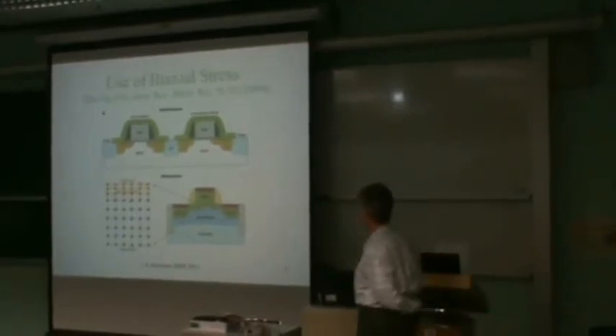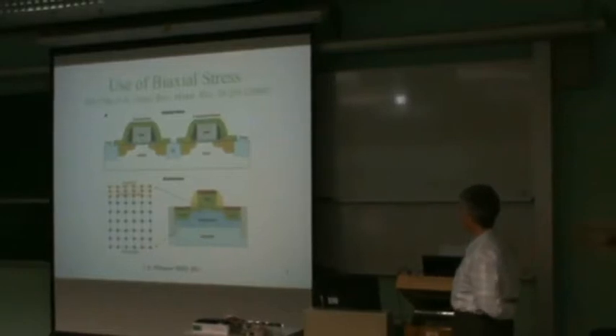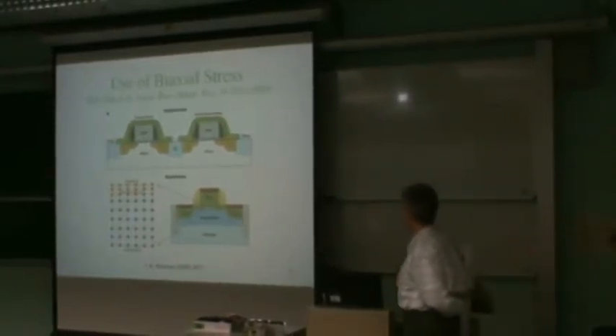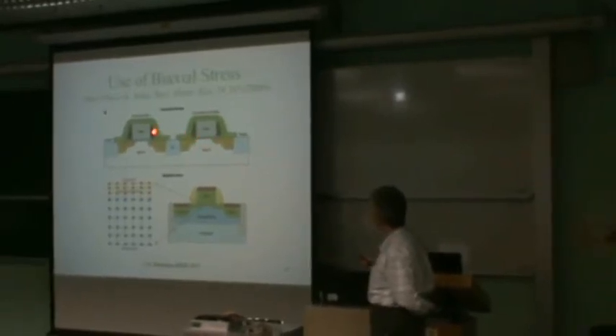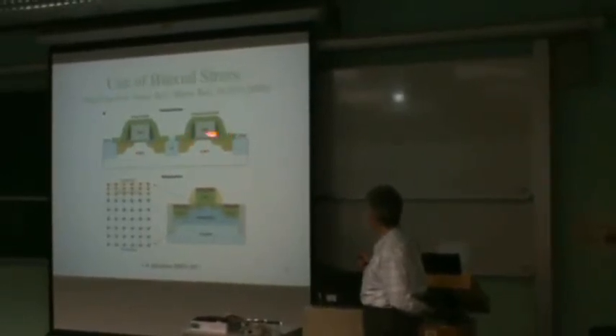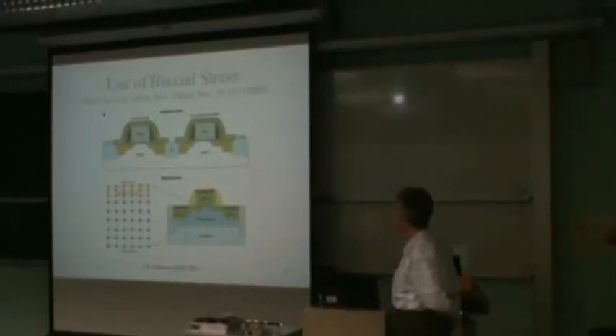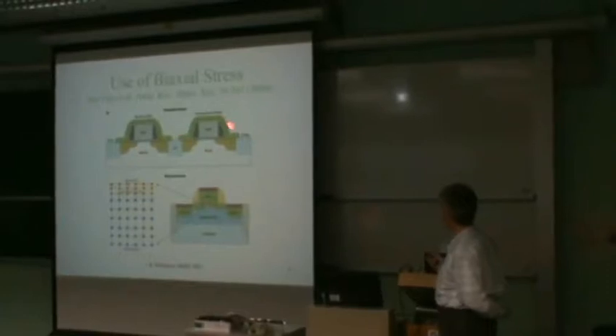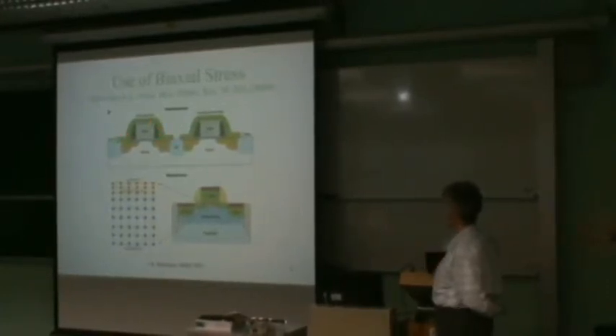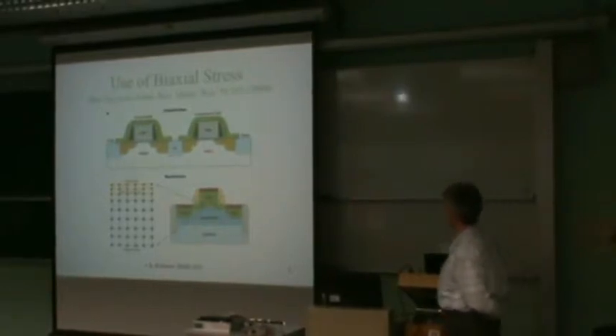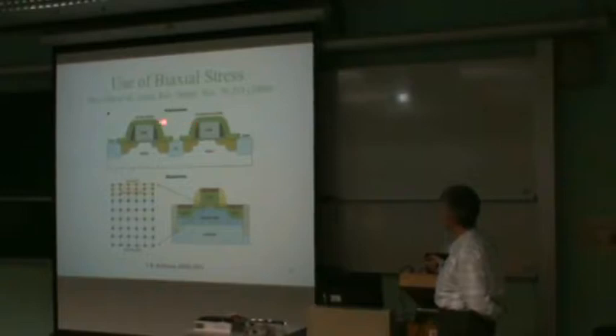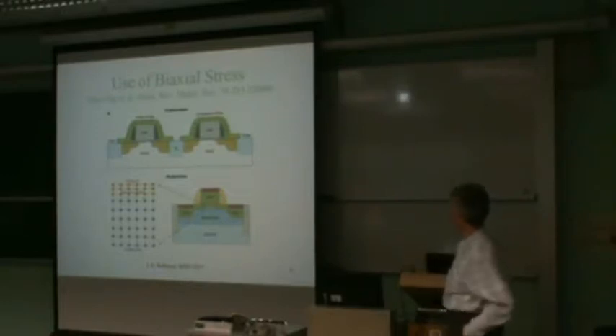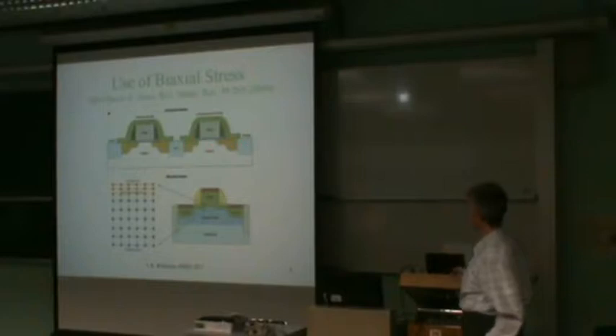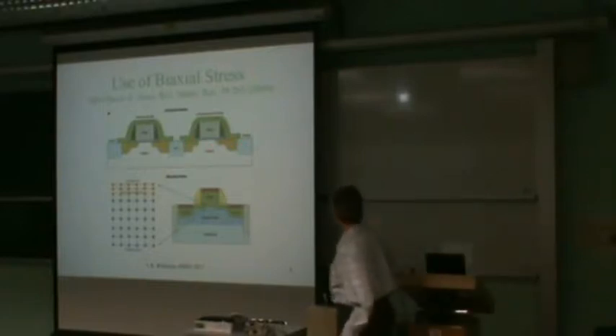so that it will get a biaxial stress in the tensile direction. And as was just explained, that's the direction that improves the mobility for NFETs. And so when you go into a CMOS technology, you need an NFET next to a PFET, and you need to stress these in opposite directions, as explained, because of the piezo-resistance coefficients. And that can be done by using different materials for the stressor structures, which are built on top of the devices. So this would be a way of applying a uniaxial stress, because the stressor structure is a cylindrical structure that runs along the entire channel, and so stress is only in the direction in the plane of the screen that's seen here.